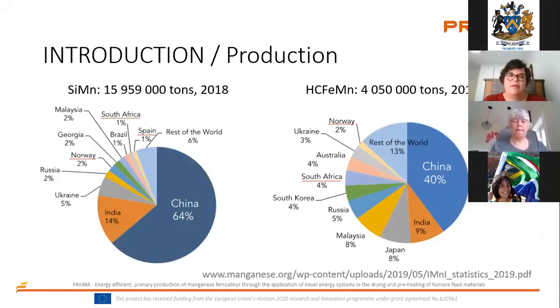On this slide, on the left-hand side, you see silica manganese production. It's actually much more than high carbon ferromanganese. Steel producers prefer the silica manganese because of the type of inclusion that's forming in the steel. If they don't use silica manganese, they use ferrosilicon and high carbon or medium carbon ferromanganese production. And my understanding is that the inclusions are different, which creates problems downstream with the casting and with the processing of the steel.